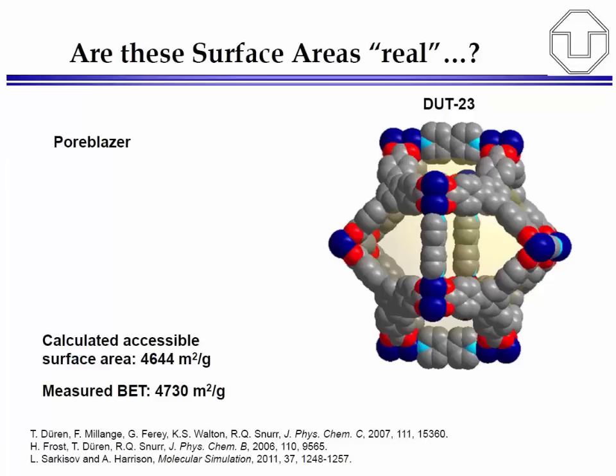It shows basically, and here the work from Tina Düren was extremely useful. She has developed a theoretical method that basically uses a nitrogen molecule and rolls it over the inner surface area. So in this way, the accessible surface area can be calculated theoretically, just from the crystal structure, from the geometrical van der Waals radii, and so on. The theoretical surface area can be calculated, and it shows that the surface area here is 4,600 square meters per gram. So it is a real geometric accessible surface area.